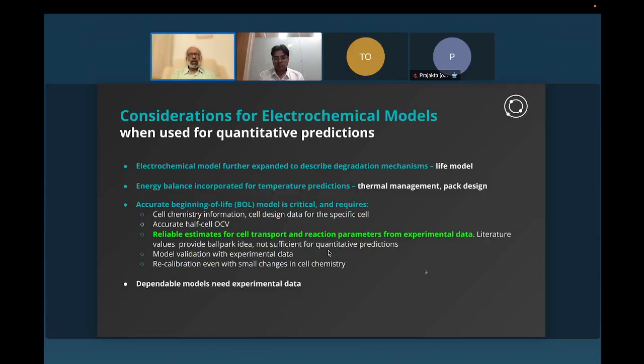Again, as I said before, there are values available in the literature. They are only ballpark numbers. If you really want good quantitative prediction, we need to estimate these for the cell at hand and not just rely on what's published in literature. We need to validate the model with experimental data, and there may be data, everything is set up for one type of cell. If there is a small change in the cell chemistry, we need to do this process all over again. Again, these are required if you want good quantitative predictions.